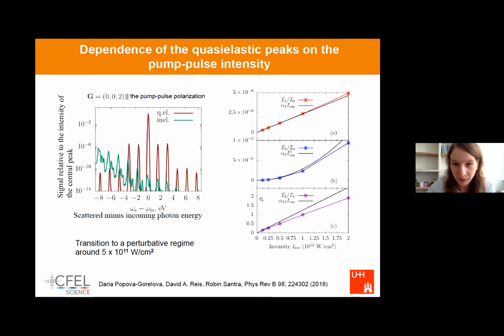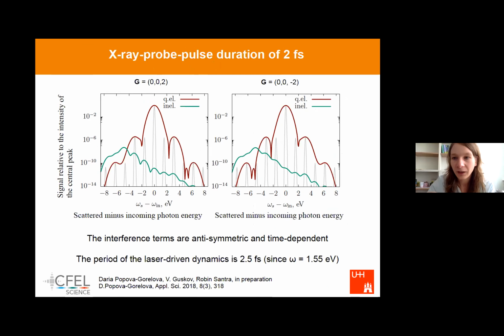So far I was speaking about time-unresolved X-ray optical wave mixing, meaning that the X-ray probe pulse is long in comparison to the cycle period of the driving pulse. But now the next question is what would happen if we want to be time resolved? Here the period of the laser-driven dynamics for omega of 1.5 electron volts is 2.5 femtoseconds. And here we consider an X-ray probe pulse of duration of 2 femtoseconds. So it is now subcycle resolved.